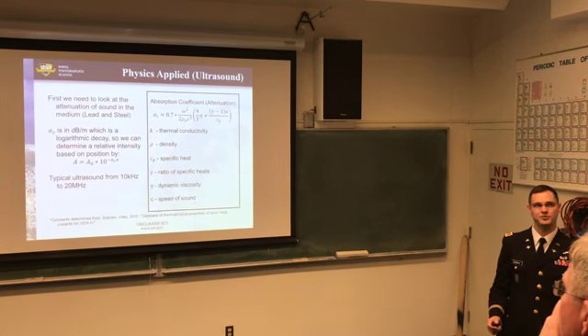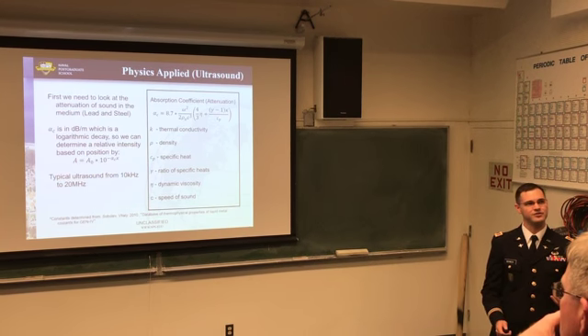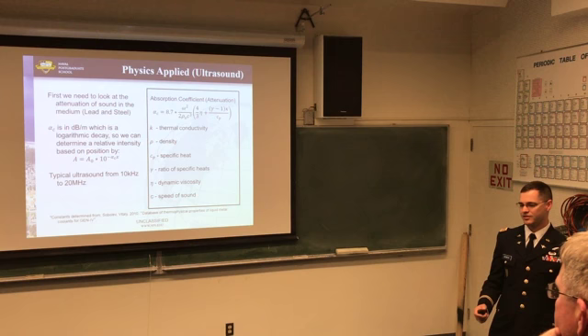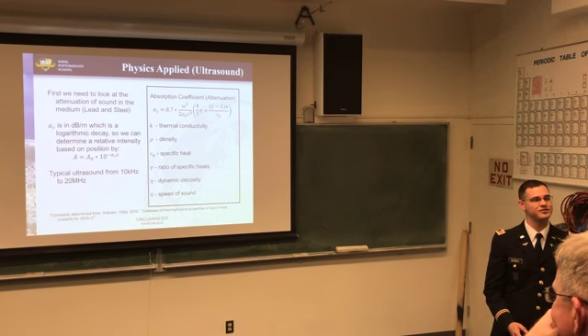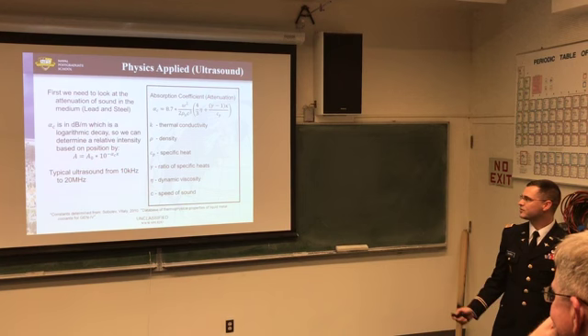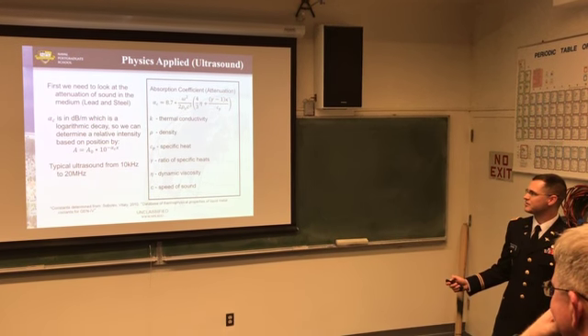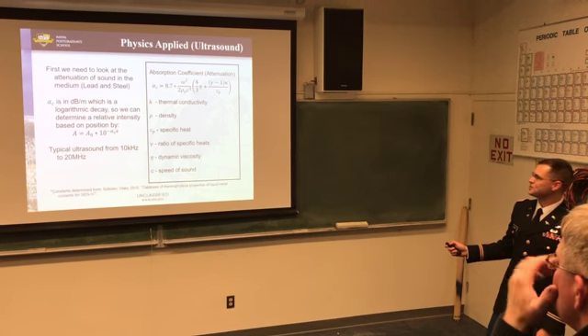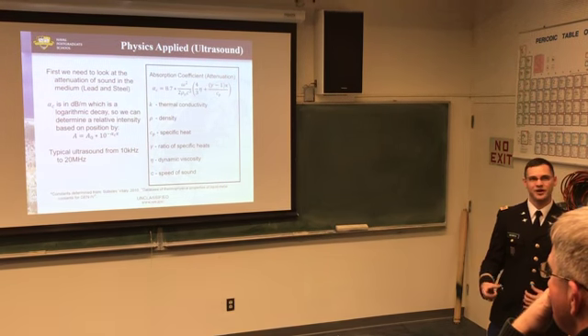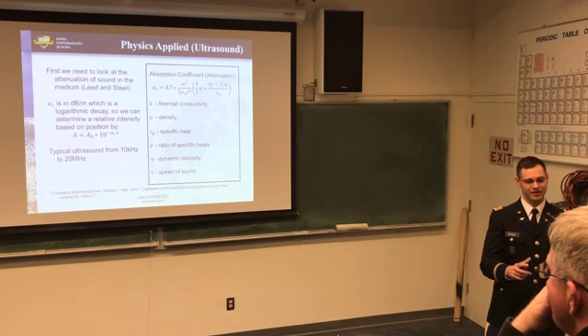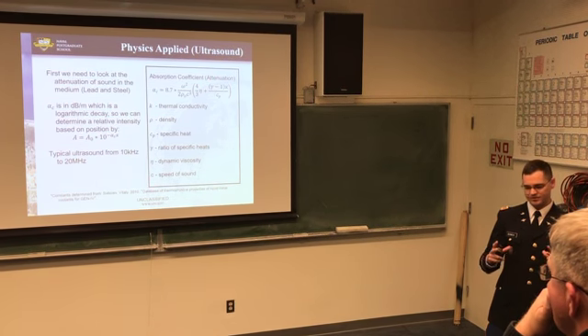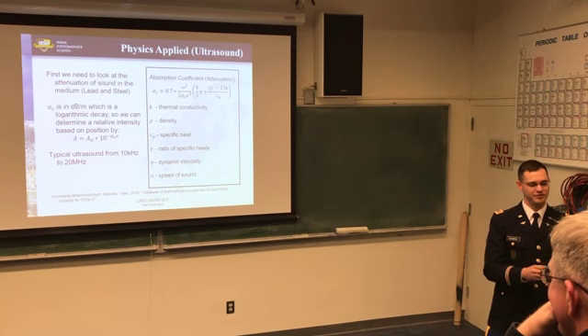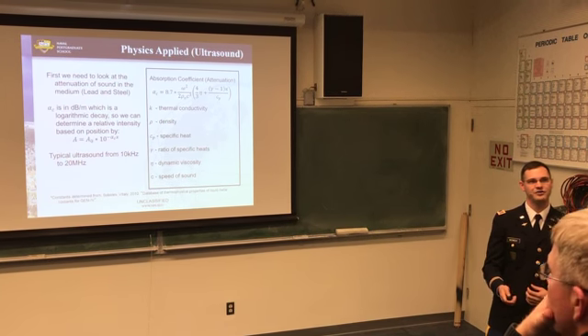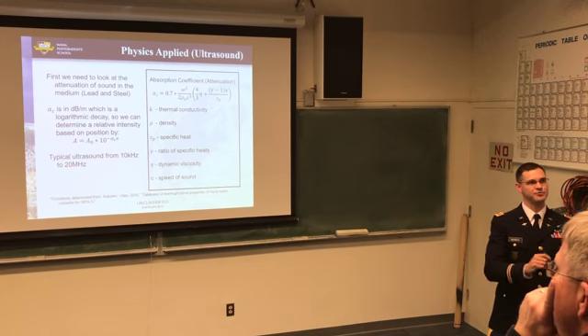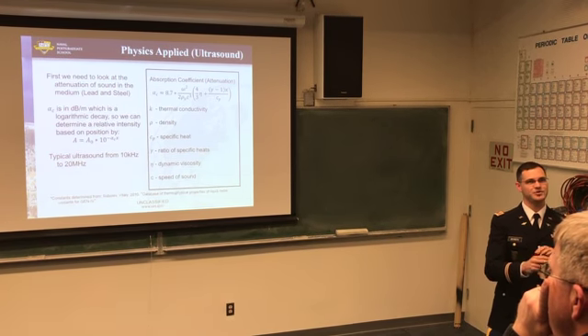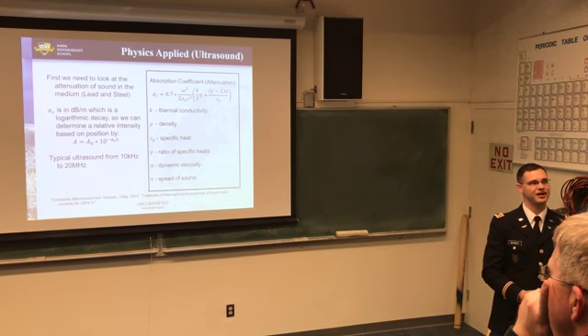So for ultrasound, the 3 main things we're going to look at are the absorption, so how much sound gets attenuated in whatever medium you have, the reflection and transmission, and then just checking the far field conditions to make sure that we can simplify the problem. So first, the attenuation of sound in lead and steel is a very large equation. So in order to find all these constants, we actually found a book that had a database of thermal physical properties of different materials that were going to be used in advanced reactor design. And all those had a lot of tabulated data, some best fit curve lines, and you plug in your temperature and your material properties, and it spits out a constant for you.